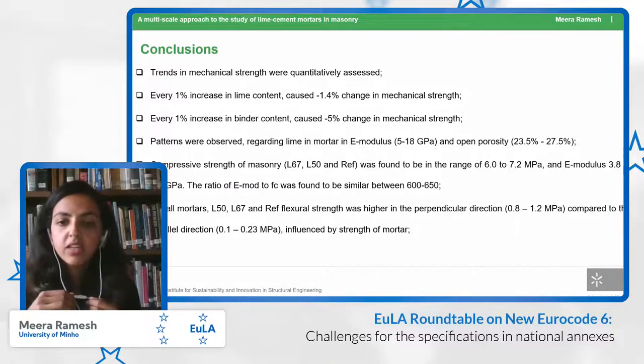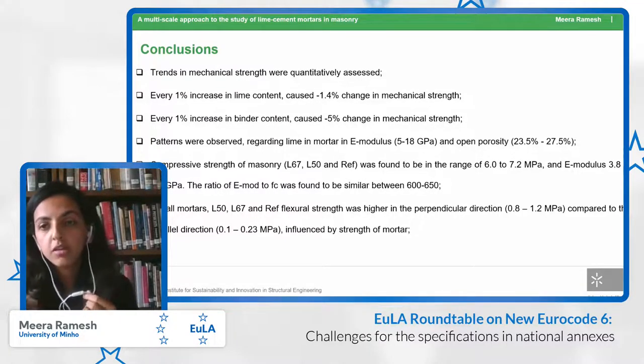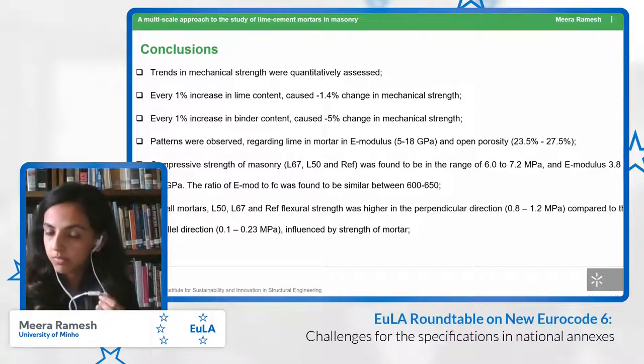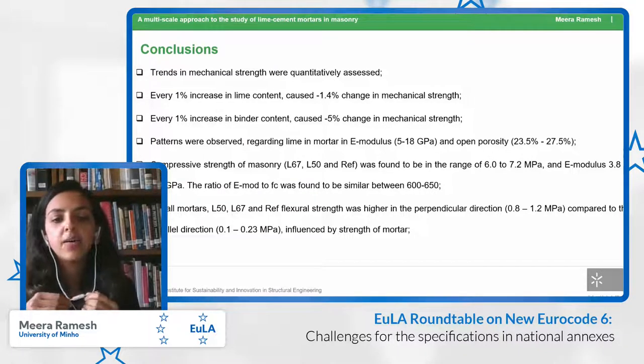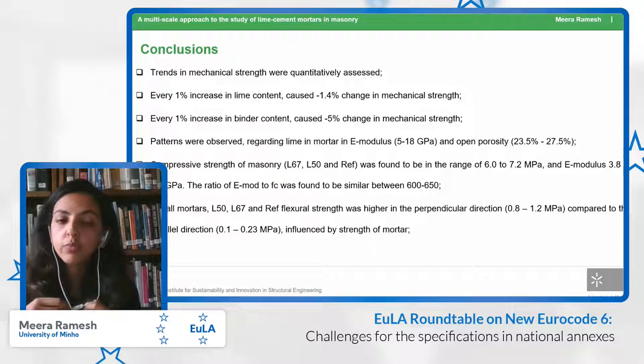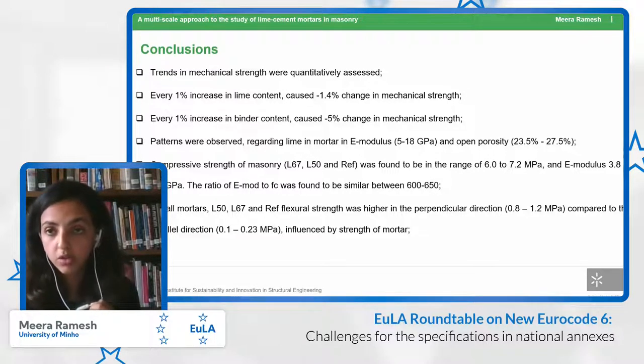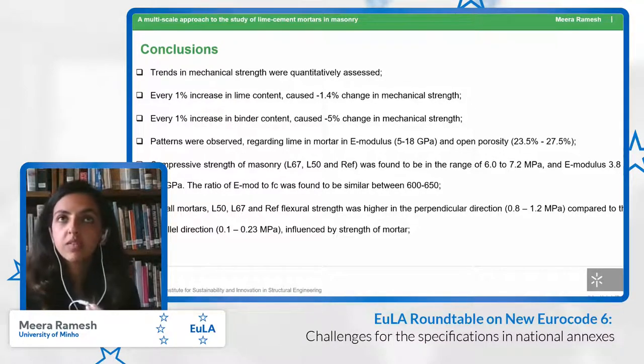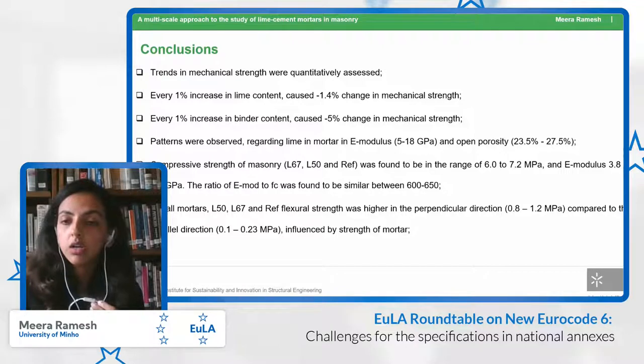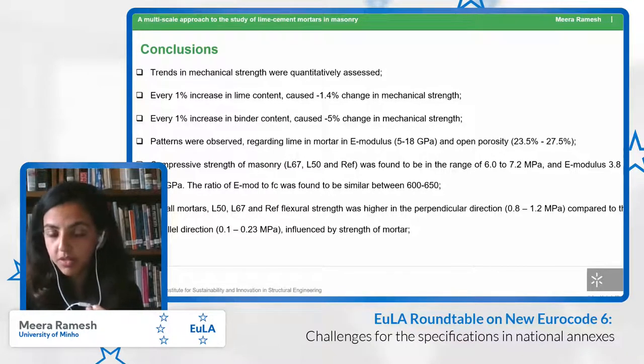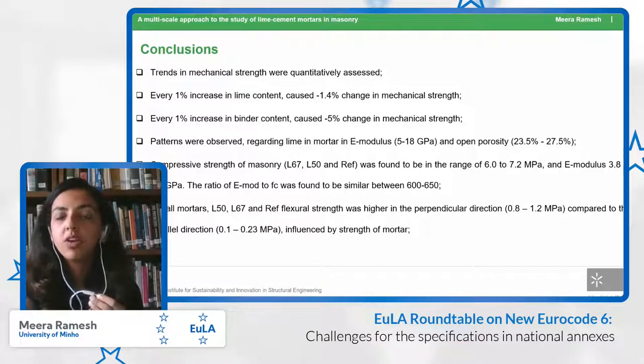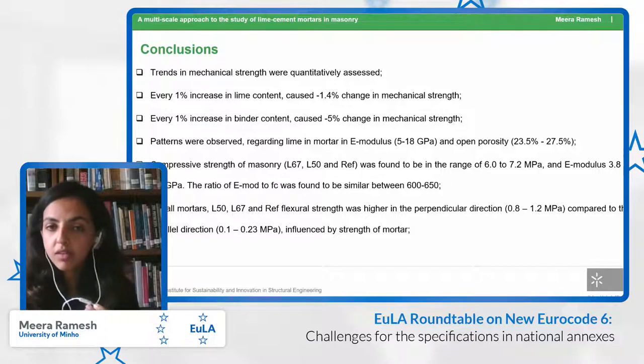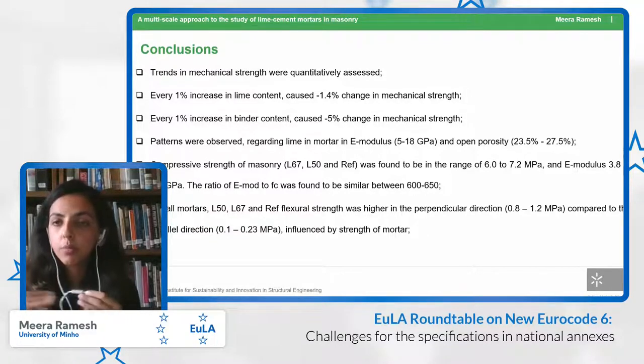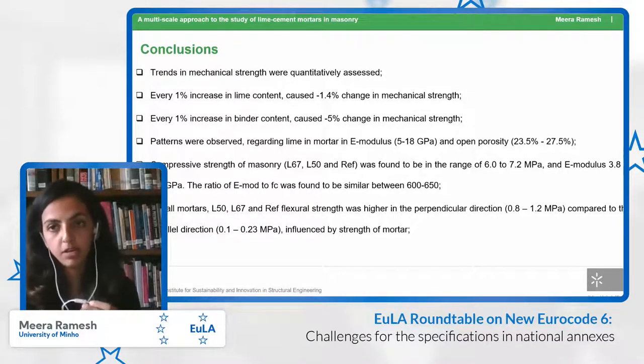For flexural strength, we found that all values were higher in the perpendicular direction, which is as expectable. And the results were influenced much more by the compressive strength of mortar rather than the presence of lime in the mortar. So as an overall conclusion, one could say that if you used two mixes with comparable compressive strength, regardless of the quantity of lime present in them, at the masonry level, the properties tend to be similar.